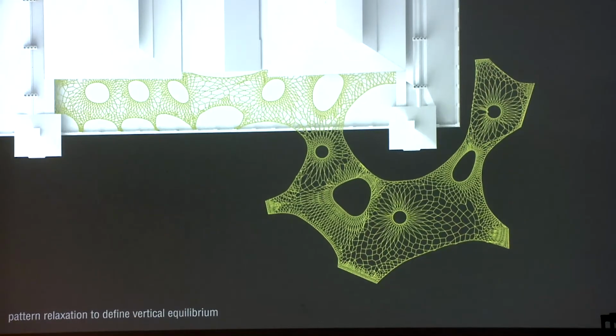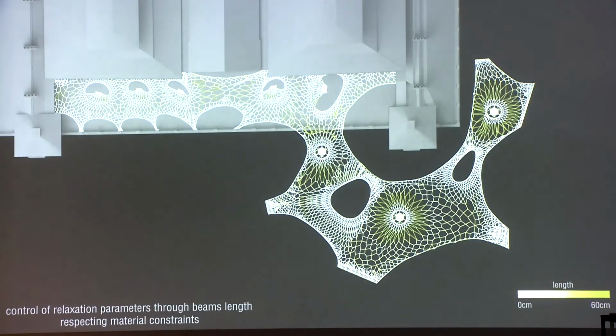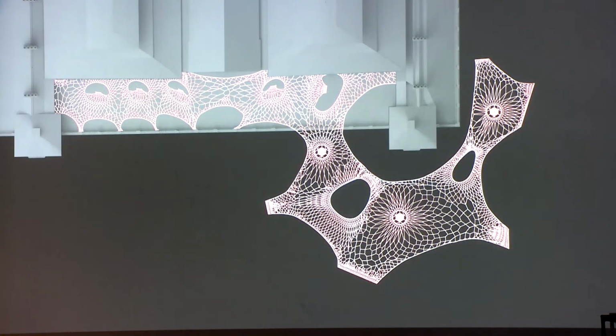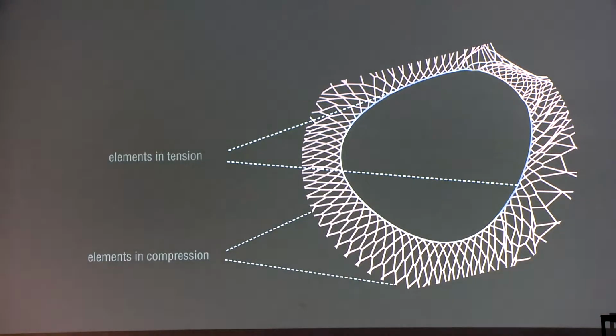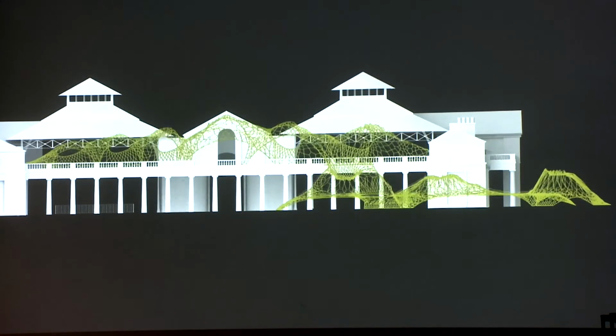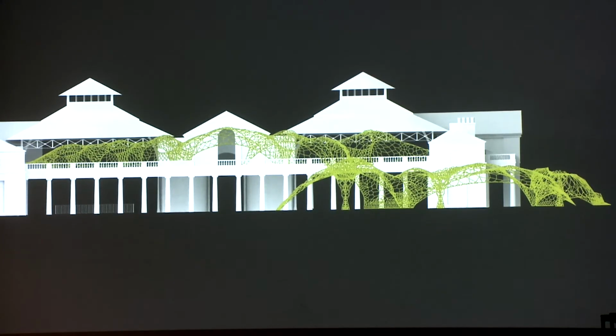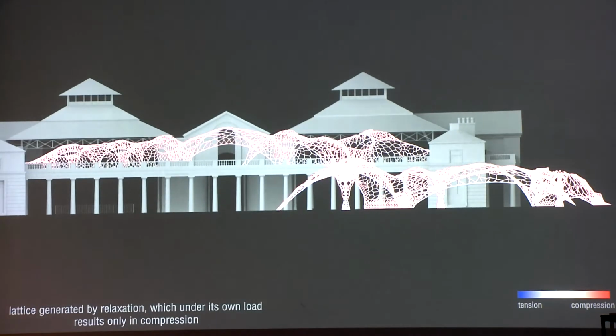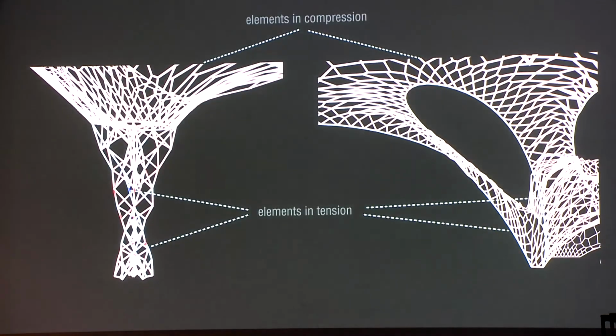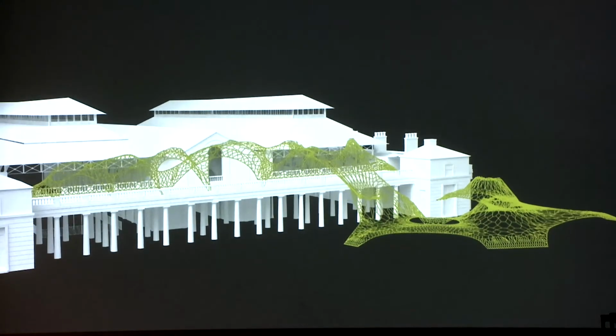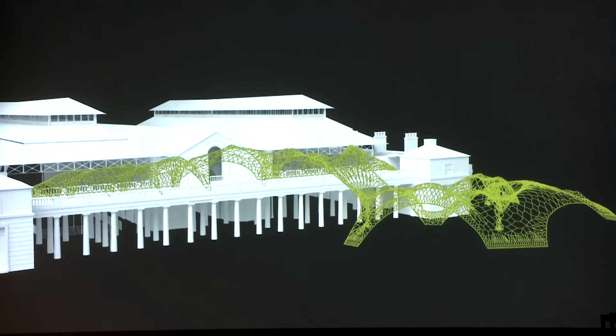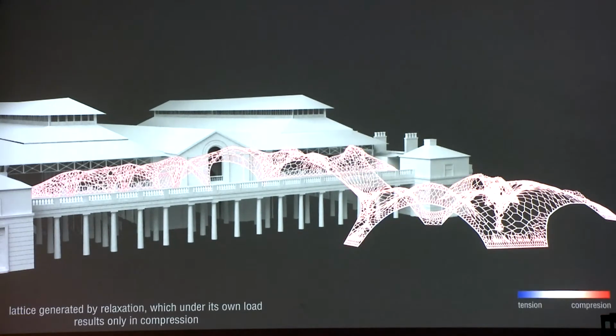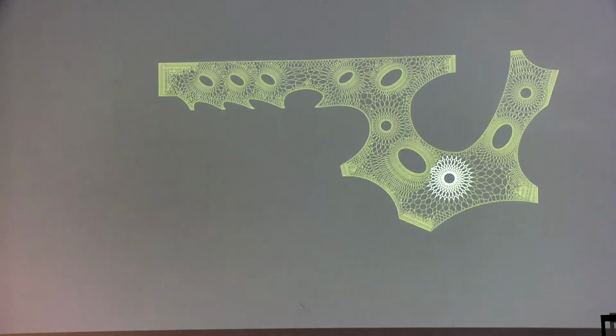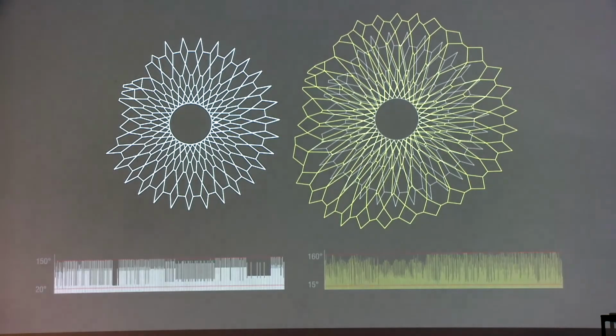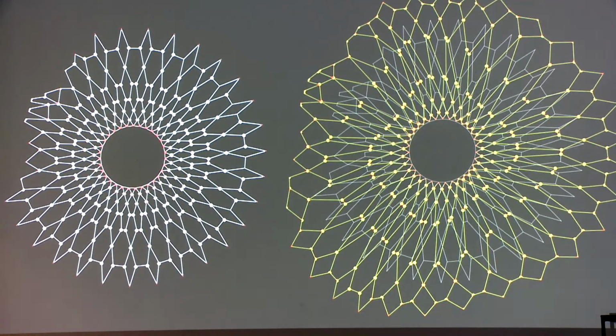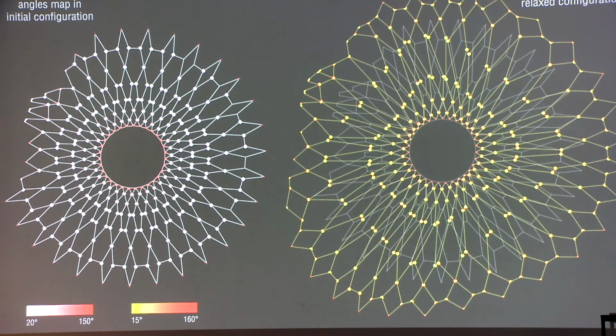Then we relaxed this structure in order to respect the material behavior that needs to work mainly in axial forces. As we can see, we are achieving a network that is mainly working in compression and in tension. Tension happens mainly in the closed boundaries. We are controlling the parameters of this relaxation, taking into consideration the maximum length that the material can achieve. So we relax the system in order to keep the maximum length at 60 centimeters. At the end of this process, we are evaluating and controlling the angle distribution, which is another important material parameter for our system. And we can observe from the map and the diagrams that the distribution is changing within a 5% value, so it is perfectly feasible with our material parameters.